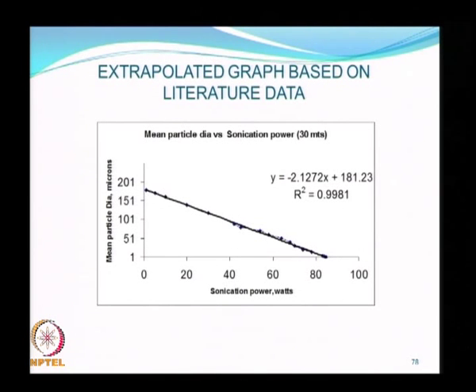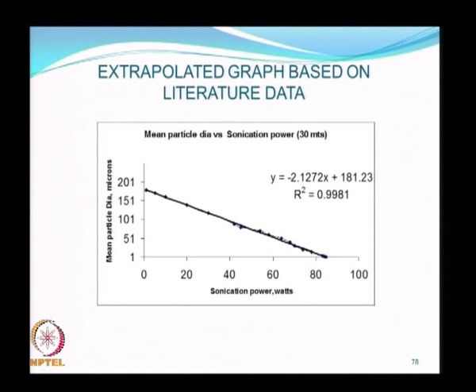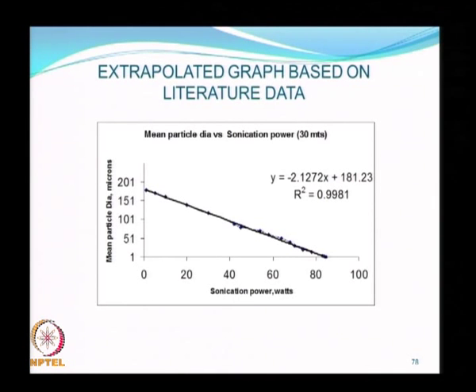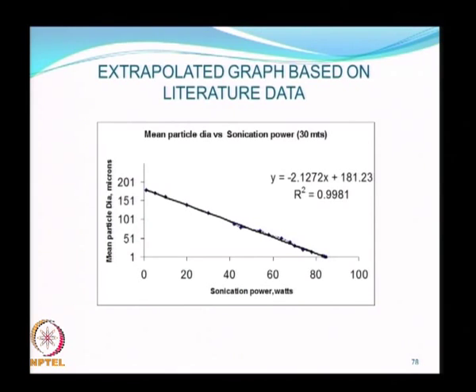Plotting all literature data as mean particle diameter versus sonication power in watts shows that with increasing sonication power you can drive the mean particle diameter after 30 minutes of sonication down to 1 micron. There is not much work reported for particles smaller than 1 micron, and it is reasonable to expect that the relationship cannot simply be extrapolated—there will be a leveling-off effect even with sonofragmentation. However, it is reasonable to expect that sonication will remain viable technology even for particles smaller than a micron.